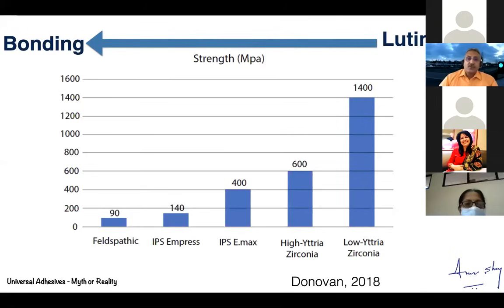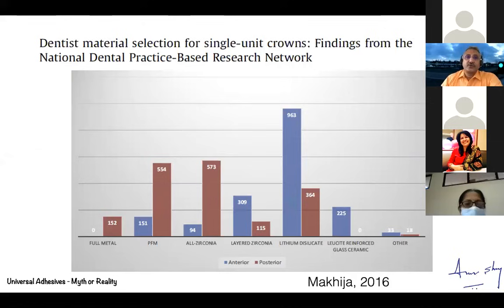So as I told you, as the strength decreases, there is more of a need for bonding. Now, if you look at the left side of the screen, you see feldspathic and IPS Empress and Emax. They have strengths of 90, 140, and 400. But I also showed you veneer cases which are done with these materials, which withstand with a success rate of 82% over 20 years because they are bonded. So as you are going towards lower strength, you cannot use glass ionomer, you actually need to use bonding.